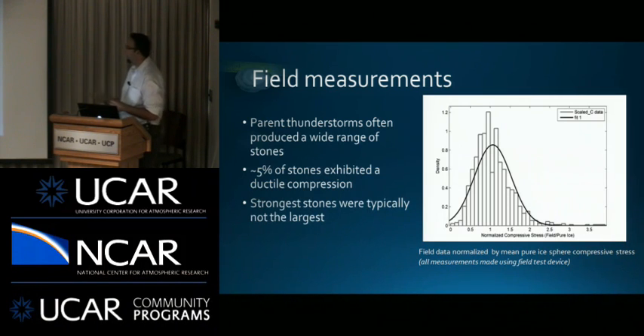So you go from very slushy stones that simply compress under maybe 16 pounds of force. And I'm going to flop units because I work with engineers all the time, and so we jump back between metric and English. And then you'll get other stones that are extremely, extremely hard. And I actually saw this in the field a couple weeks ago. We essentially maxed out the strength device. We applied over 700 pounds, exceeded the range of the load cell, and the stone did not fracture. So that stone itself, I have no idea what about it made it so tough, but it did not produce a fracture, nor did it compress.